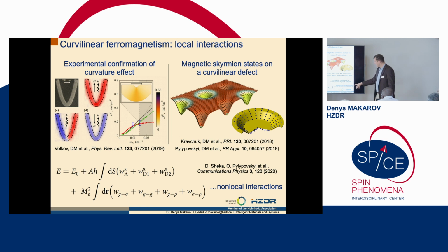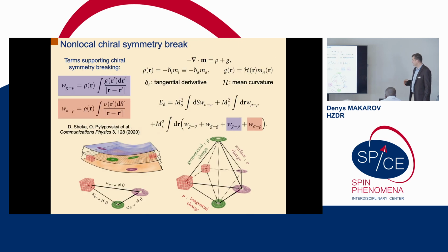But there are non-local interactions, and this is the work of Denis Sheka and Alexander Pylypovskyi, where they really tried to explore the impact of magnetostatics in general, not only local magnetostatics when you have anisotropy, but also non-local magnetostatics. And the funny thing here is that you can come to the point where you have the possibility to have such energy terms, which are shown here, which, simply believe me, because now I'm skipping, like, I don't know, 30 pages of analytics, but you can believe me that these terms support chiral symmetry breaking. So basically, there will be two domain walls, for example, which are energetically different.